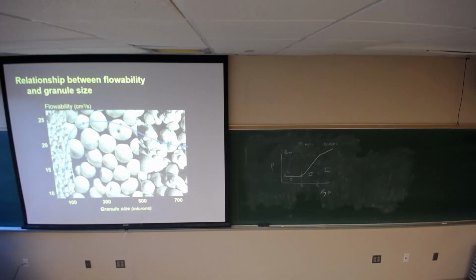So the Spaniards looked at spray-dried granular size, and they realized that the flow behavior, which is on the y-axis here, is sensitive to the size of the particles. I put these images behind here, and the images don't really do us justice, although they do illustrate some things. If I have small particles, they don't flow very well. Okay, there's more drag in the system.